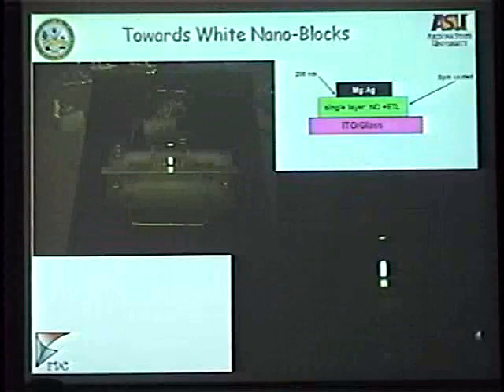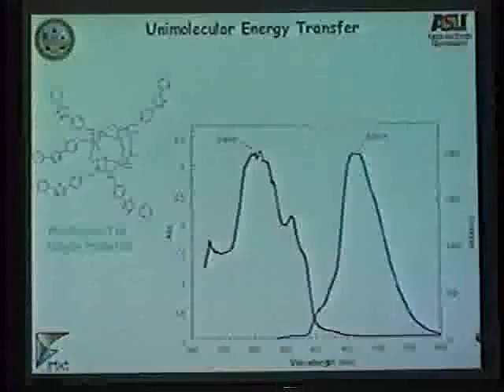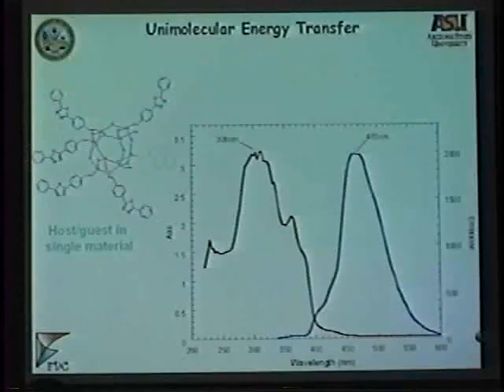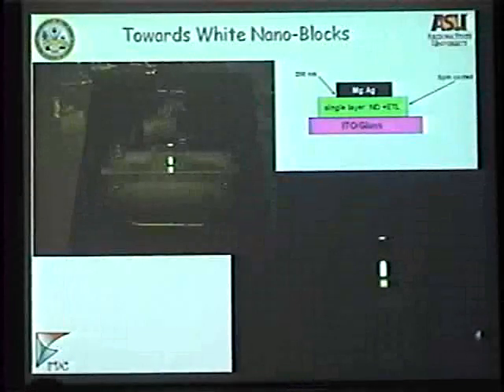And recently we were able to form whitish light. It's not completely white. There is still a yellow component in it, but it is a single layer, single molecule, single structure like this. We modified the contents here to see whitish, and that's the ultimate aim, to really have a very nice white that is used not only for solid state lighting, but also for displays, because you could simplify the display design. You don't need red, green, and blue anymore. You just put the white and use the current LCD manufacturing capabilities to put the color filters, and you have a similar display as the LCDs right now, with an integrated white light and a much simpler design than what people do right now in OLEDs.